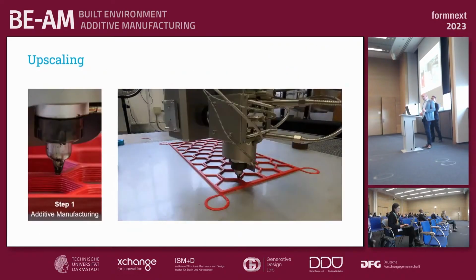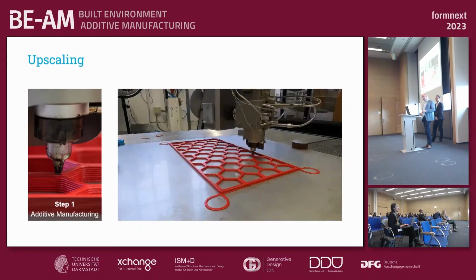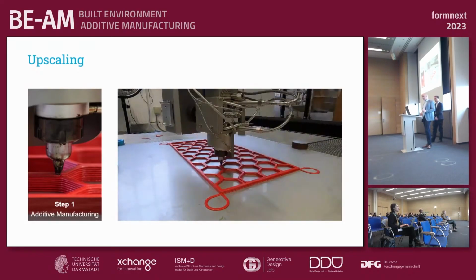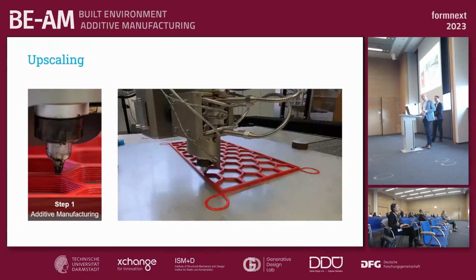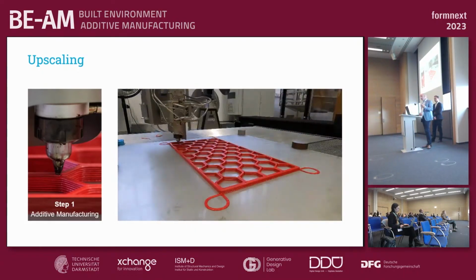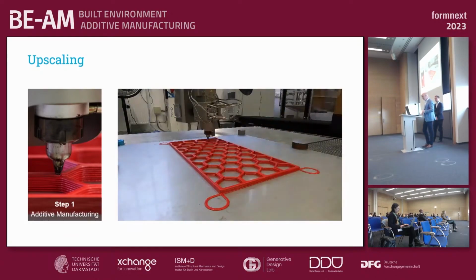So how do we do it? We can print different kinds of polymers, either with or without glass fiber reinforcement, and opaque or also a bit more translucent. We prefer to print on a flat piece. So here we're printing on aluminum, which is heated from the bottom by the heated bed. But later you also see that we print on glass directly to have a very smooth surface to glue to.